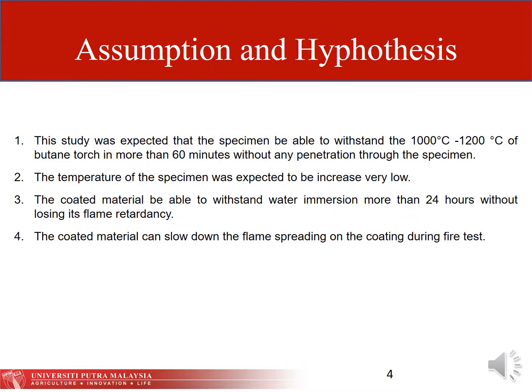For the assumption and hypothesis of this study, first, it was expected that the specimen would be able to withstand around 1000 to 1200 degrees C of butane torch for more than 60 minutes without any penetration through the specimen. Second, the temperature of the specimen was expected to increase very little. Third, the coated material would be able to withstand water immersion for more than 24 hours without losing its flame retardancy. Finally, the coated material can slow down the flame spreading of the coating during fire tests.